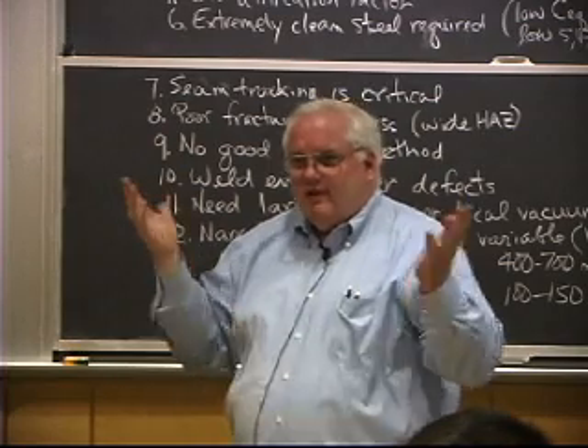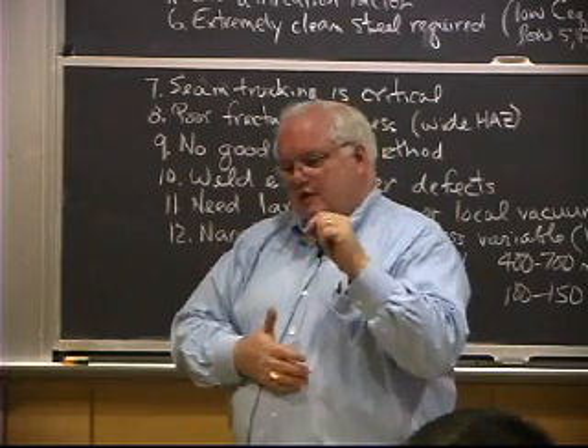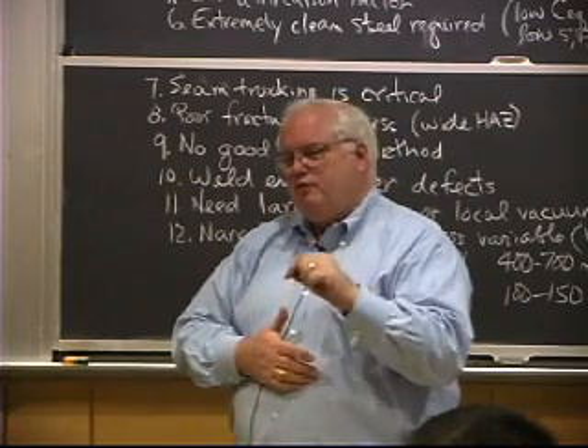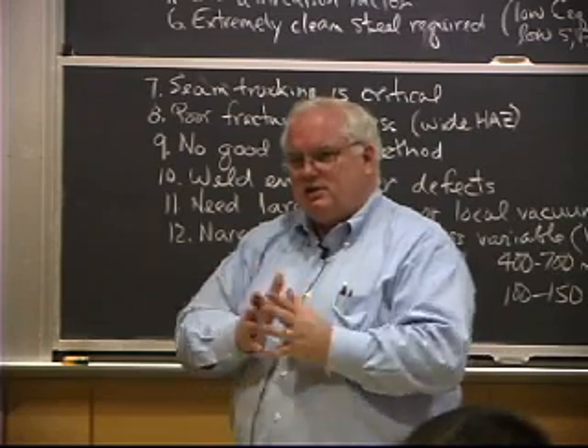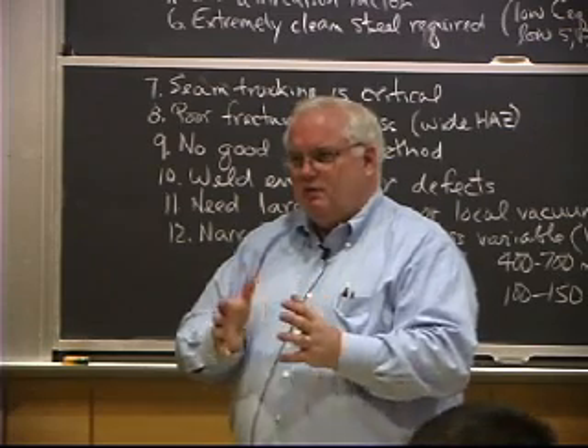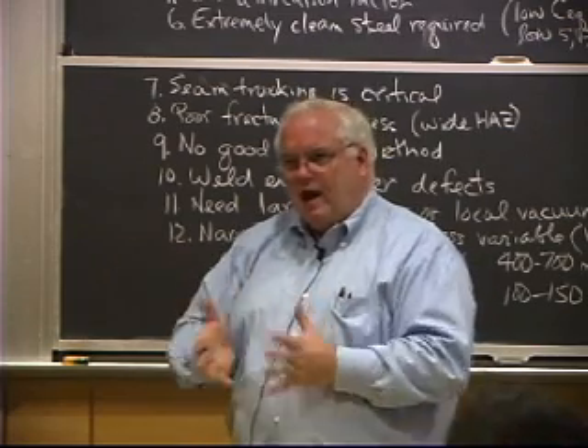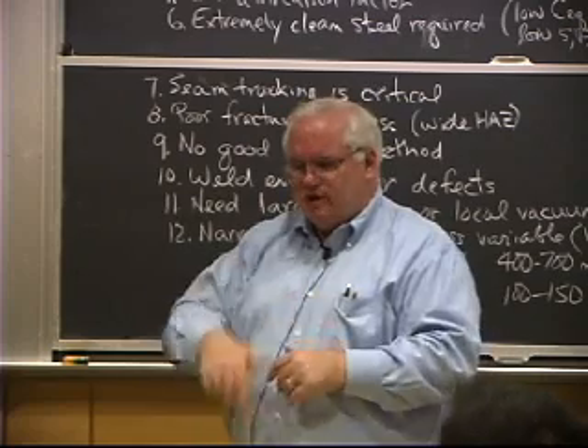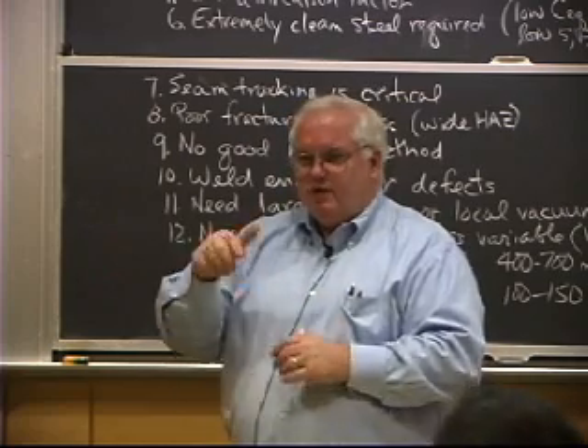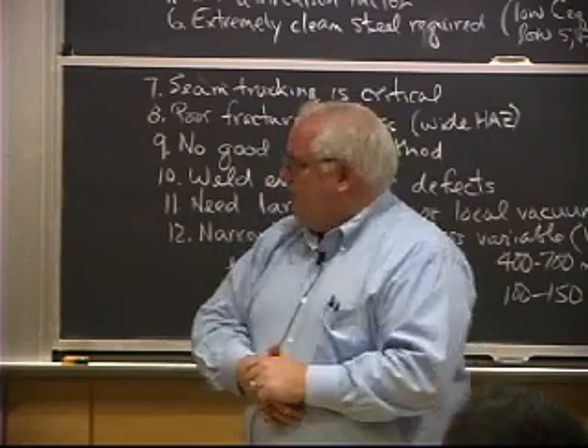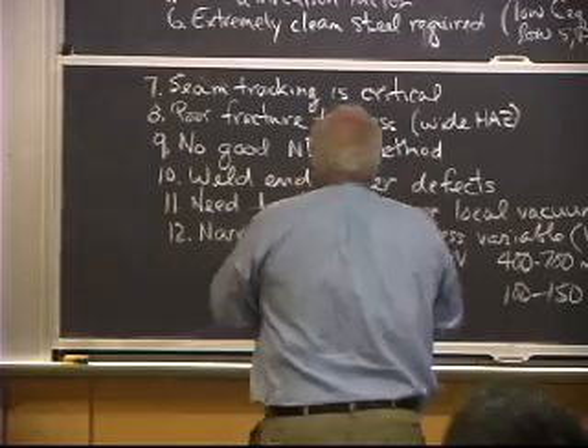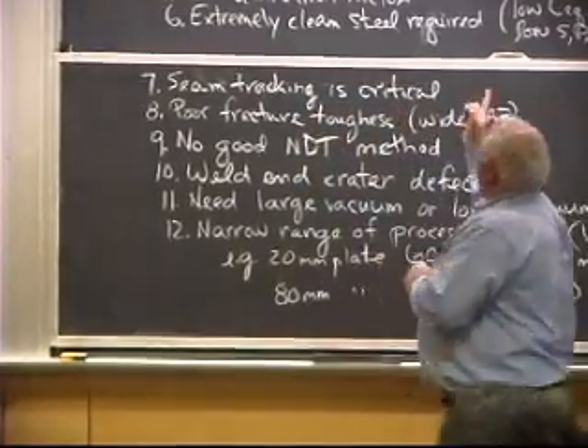And if you lose your beam for more than about 10 or 20 milliseconds, that's the inertial time constant of that liquid pool, and the whole thing will collapse. Your cavity will collapse, and you've got to drill a new hole. Well, you've been moving along, and you just produced a defect. So they never did solve the long-term beam stability problem.